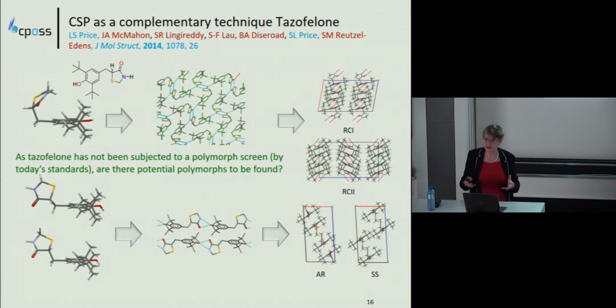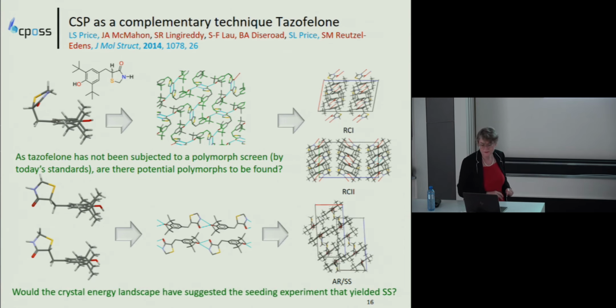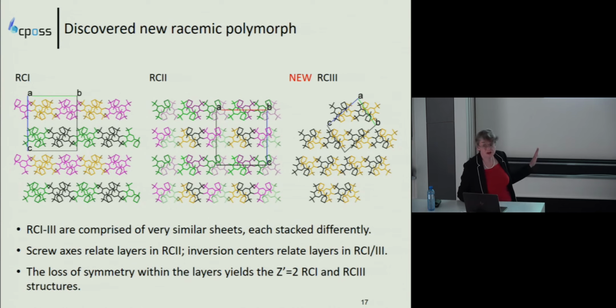But if you seeded a racemic melt with the enantiomer pure crystal, you got the very worrying solid solution with the same structure. So actually you were absorbing the molecule of the other hand, which is not what you want to do for chiral resolution. So could we suggest that? They were going to do some experiments. First thing they did, pull out of their sample a new polymorph, which was related to the other 2 they knew about, same layer, but different symmetry relationships for the stacking of the layers.